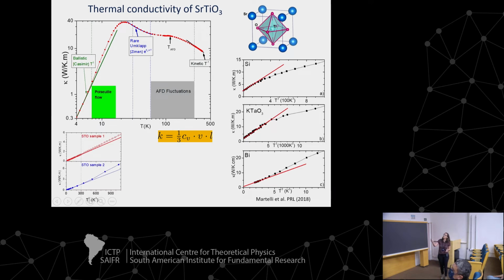If we look in the literature, the typical behavior of this region is T-cubed, mainly because of the specific heat. So we expect to have the T-cubed behavior in this region. Usually, between the peak that is typical of a crystal and the T-cubed region, we have a lower than T-cubed power law. We can see this in the large majority of materials, so this is typical behavior. But there are a very small number of materials that show different behavior, for instance bismuth, that shows an upturn. An upturn means higher than T-cubed behavior, in other words, a very efficient transport of phonons.